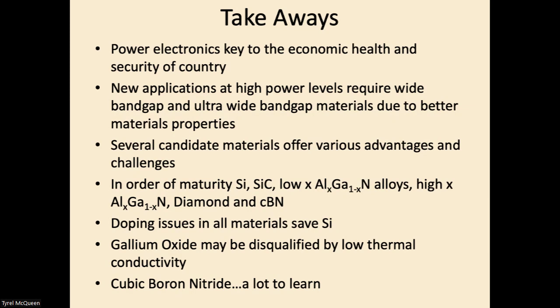In order of maturity, my words, not necessarily the field: silicon, silicon carbide, low X aluminum gallium nitride alloys, high X aluminum gallium nitride alloys, diamond, and cubic boron nitride. Doping issues in all materials save silicon. Gallium oxide may be disqualified by low thermal conductivity, and we have a lot to learn about cubic boron nitride. So that's my story. Thank you.